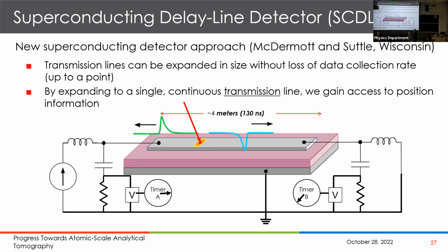And this propagates at the speed of light in this medium, which would be about a quarter the speed of light in vacuum. And then if there's a negative pulse going this way, then there has to be a positive pulse going the other way. So how do you detect, first of all, if there's a pulse? Well, all you need to do is put a sensor at the end, but actually we want to know where along this line the energy hit. And so if you put a clock at each end, then you look at the time difference between the two clocks. If the time difference is 0, it must have landed in the middle, and a positive time difference gives you some position on the right, a negative time difference a position on the left.